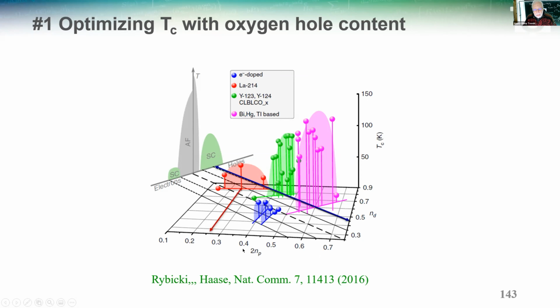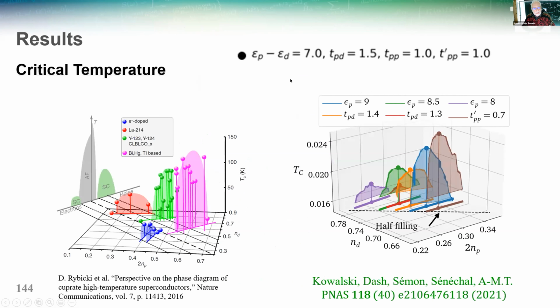You see that there's a clear correlation between the maximum TC that you can reach within one family and the oxygen hole content. The larger the oxygen hole content for the same total hole doping, the larger the TC. So can we reproduce this? I start with this ionic model, where this is my unit of energy. What's important here, and the reason it's called ionic, is epsilon P minus epsilon D, the difference between the site occupation energies, is large.